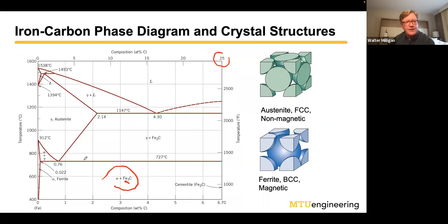Now, here's the magic about steel. It's a unique material, and people don't understand how magic this is. If I take a steel that has 1% carbon in it, for example, right here, and I'm down at 400 degrees C or lower, I have a two-phase mixture of alpha plus Fe3C. If I heat it up to above this red line here, iron is a strange material, and what it does is it changes its crystal structure. If you have pure iron, that happens at 912 degrees C. If I have this alloy here, it happens at this temperature here. But once I get up here, now I have a single phase material.